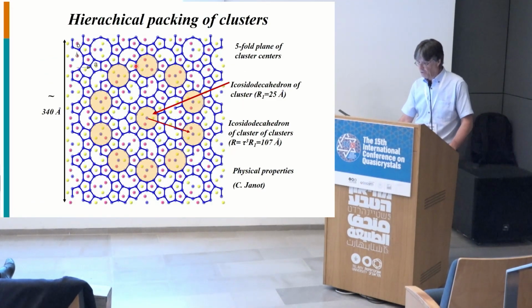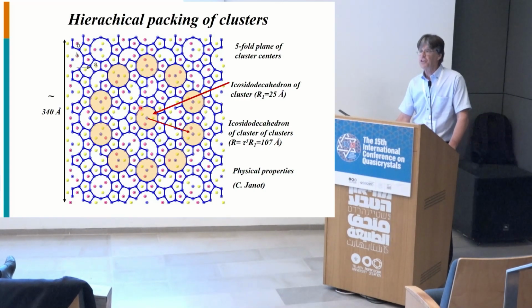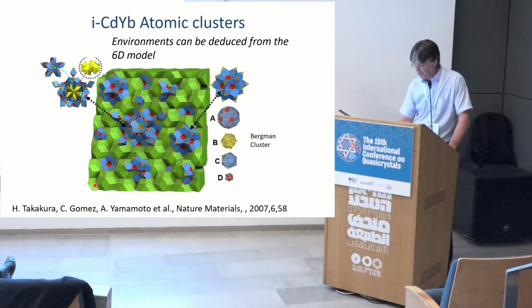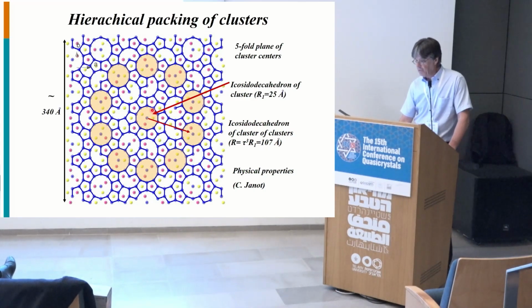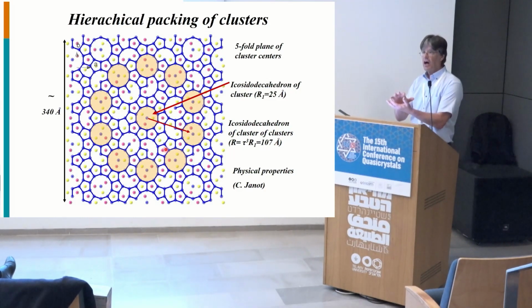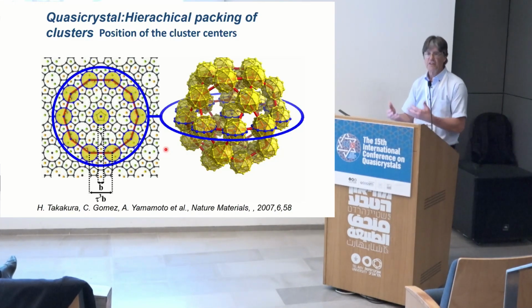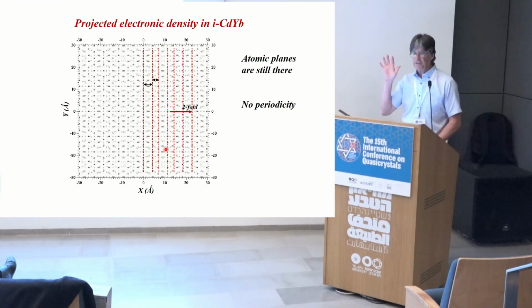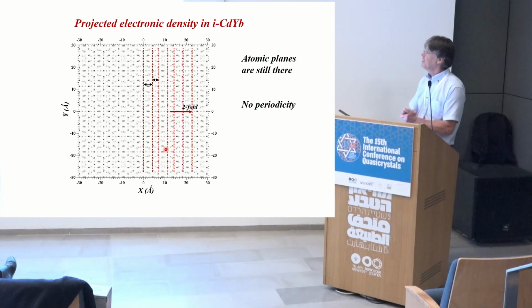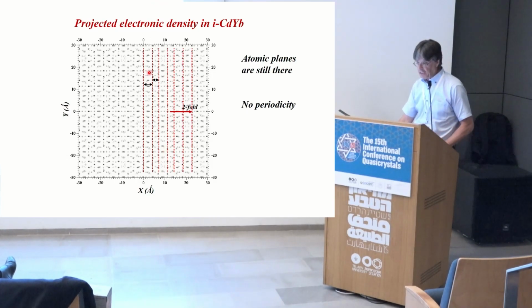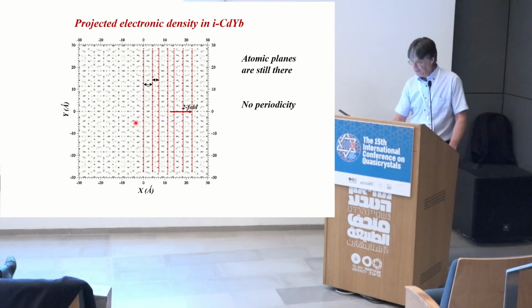I will show you more examples here. Here, what is shown is not the atomic distribution, but just the position of the clusters. So each dot is the central part of this big green cluster that is shown here, right? So we see we have a cluster here, we have a cluster of clusters, and then we have a cluster of cluster of clusters, and that goes to infinity. So one has a hierarchical signature of the structure, which is, again, a signature of this quasi-periodic long-range order. Also, if we look at what's going on in projection, this is not completely random because this is ordered, and we can clearly see that this is the projected electron density. We have dense planes perpendicular to the twofold direction.